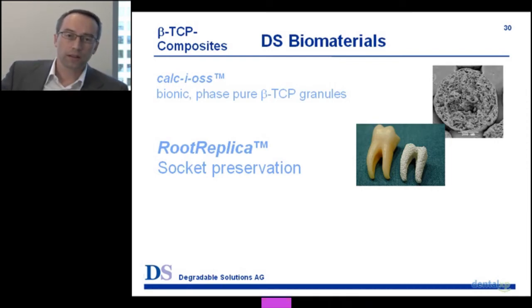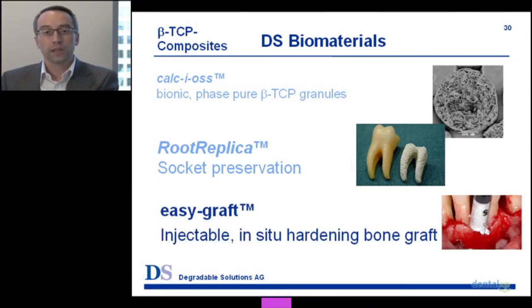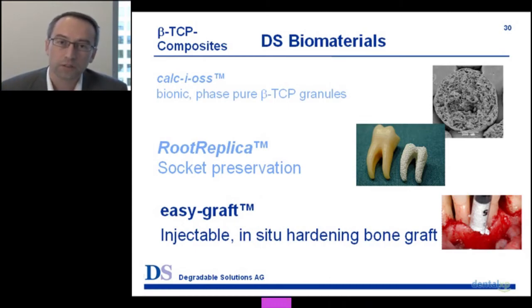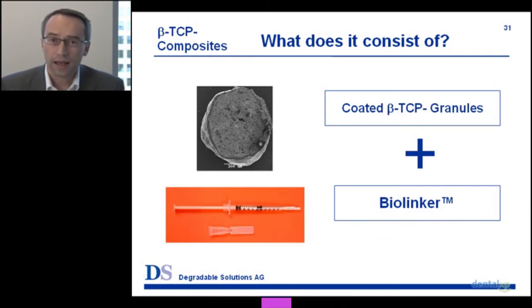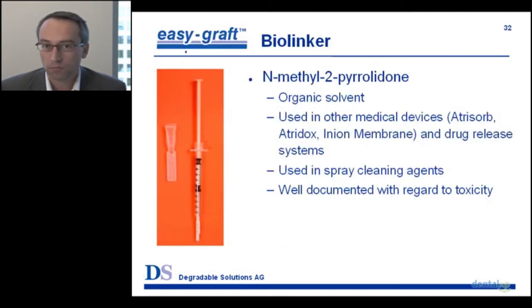On the top left you can see the granules with the coating. Here the coating is presented way thicker than it really is. In reality it's just 10 microns. So you add the biolinker to the granules, and the biolinker, or this NMP, will penetrate this coating and make this surface sticky. You press the granules together and form a solid body, and then when it comes in contact with water or blood, this NMP is extracted again from the graft. So you have more or less a physical method, not a chemical hardening of this bone graft. And as soon as this biolinker is extracted, and we know that 99.5% is extracted within the first 24 hours, you have a solid biomaterial which stays in place.